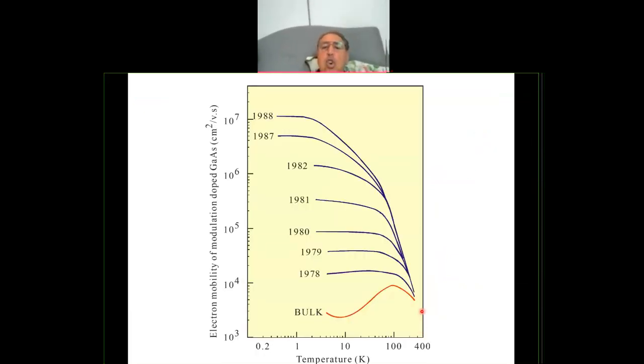So here, just to show you, for example, the mobility of some pure gallium arsenide is only about a few thousand. And then when we use this modulation doping, you can see you can reach millions, tens of millions mobility. So you increase it by a huge factor. And this increased mobility will mean operating at a very high frequency as well.